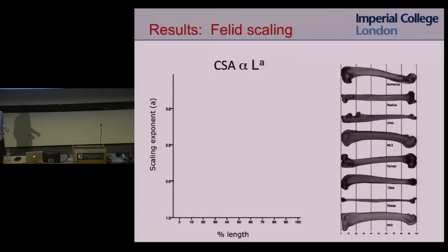So we can plot this scaling exponent, which I call alpha here, on a graph that looks like this. So now here's all the bones of the fore and hind limbs scaled to the same size, so you get an idea of the differences in shape. And here I'm plotting, for each percentage length, the scaling exponent. So this is plotting the cross-sectional areas proportional to the length of the bone to some exponent. So you'd expect if it was isometric, that means that all dimensions are growing at the same rate, this exponent would be 2. Because cross-sectional area is length squared, so you'd expect the exponent to be 2.